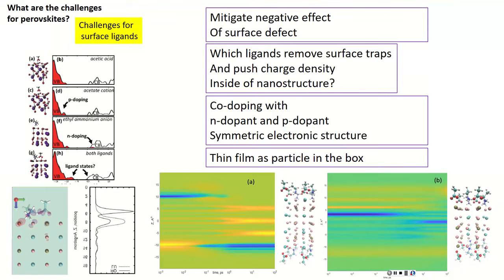So for the cesium-rich layer, calculations of Daniel show that it is either being excited only to a state where the hole stays on the ligand, or even if one starts with equally distributed inside, as time passes by, one of the lowest states would be a trap state for a hole. So bluish orange corresponds to electron, bluish corresponds to hole, and this greenish to neutral equilibrium distribution. So according to results by Daniel, the cesium-rich surface is bad for photo emission.